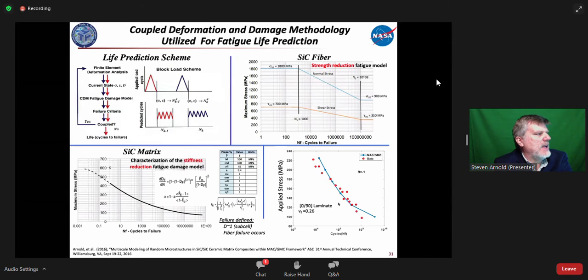Also, a little more sophisticated analysis involving fatigue. Here, we're just illustrating the implementation of a coupled deformation and damage methodology that's cyclic. I think the important aspect of the way we deal with it is we have 2 different types of failure. When it comes to a fiber, we reduce the strength of the fiber as a function of cycles, and we actually allow that strength to plateau and stop due to the saturation of interfacial effects on that degradation of the strength of the fiber.